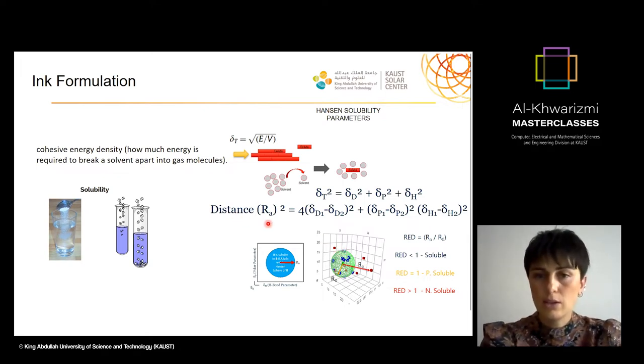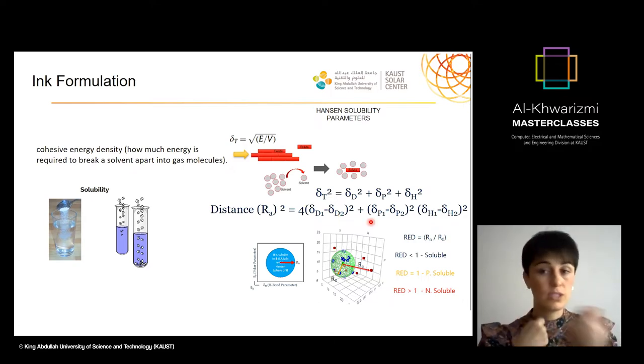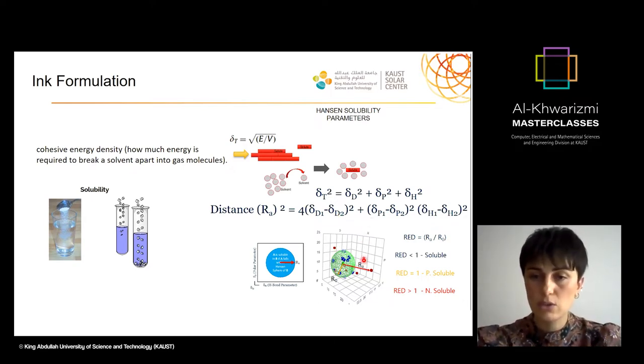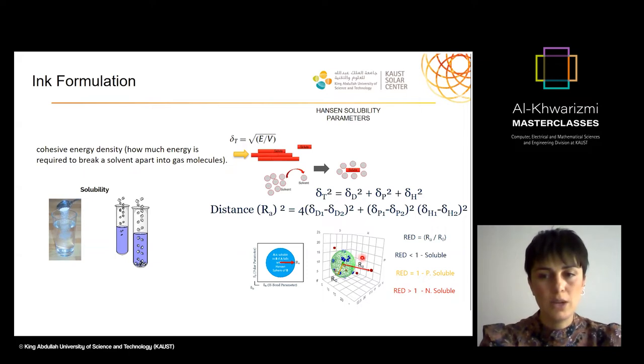So when you calculate this distance RA, considering these dispersive and polar forces between the solvent and solute, you can calculate this RA, okay? And this RA and R0 give you an RED value, okay? And if this is less than one, which means your solvent solution is within this sphere, that means you can dissolve it. And when it's outside, it means that it's not a suitable solvent, or it's called a non-solvent.